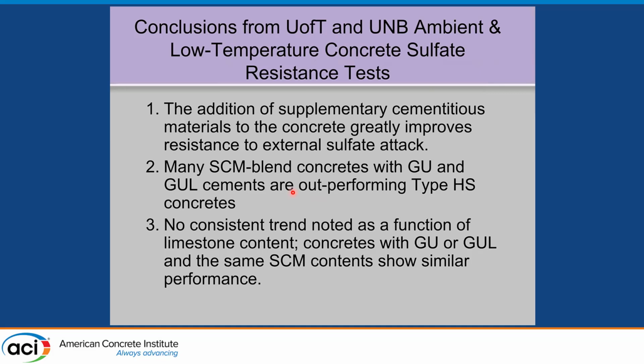So the conclusion from that joint study is that the addition of SCMs greatly improves resistance to sulfate attack. Nothing new there. Most of the SCM blends with GU and GUL cements are outperforming sulfate-resistant cement concretes that have been allowed for years. And there was no consistent trend of the impact of limestone content on the performance of those mixtures at the same SCM levels. So in other words, the limestone did not make anything worse. We didn't see thaumasite damage. We didn't see any other significant damage.